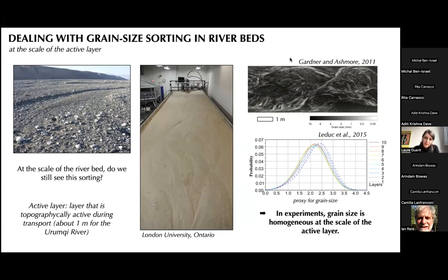Because we're in a flume, in an experiment, they were able to look at the grain size distribution at different levels within the active layer, so to have a view from inside of the grain size distribution. And this is what this figure shows here. We have 10 layers within the active layer, and you can see that most of them have exactly the same grain size distribution, except maybe for the top ones that are a little bit coarser. But on average, in these experiments, the grain size is homogeneous at the scale of the active layer, so at the scale of the riverbed.